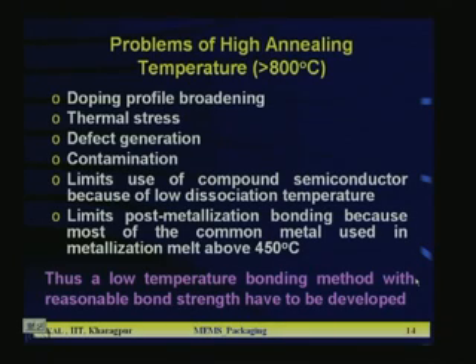The next slide shows the problems of high annealing temperature. In fusion bonding we found that temperature should be greater than 800 degree or 700 degree centigrade, so that the bonding strength is very good. But there we face certain problems. What are the problems? Those are highlighted here. The one problem is doping profile broadening. When the temperature is more than 800 degree C, in some cases you go for 1100 degree C, the doping profile broadens because the dopants in the devices, either P plus region or N plus region, start lateral diffusion, and some out-diffuse. So, the profile may change, that is not desirable.